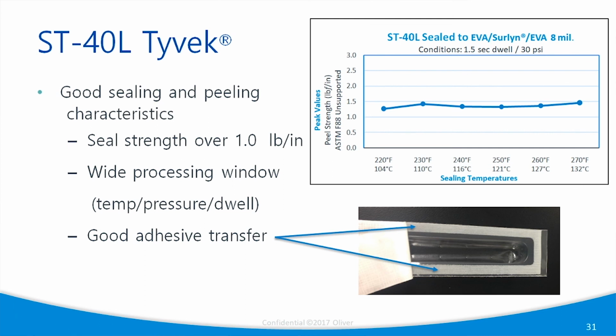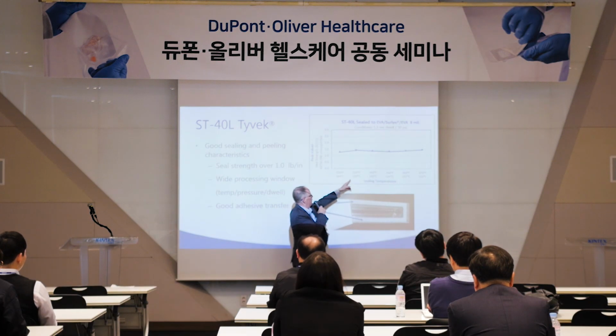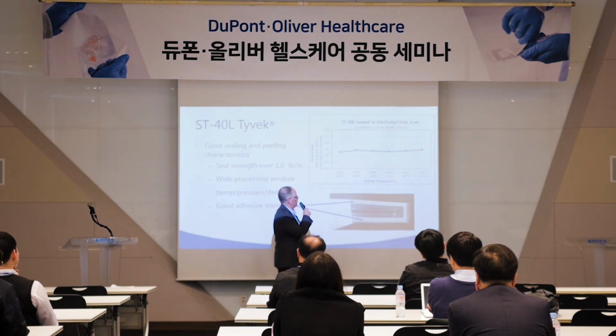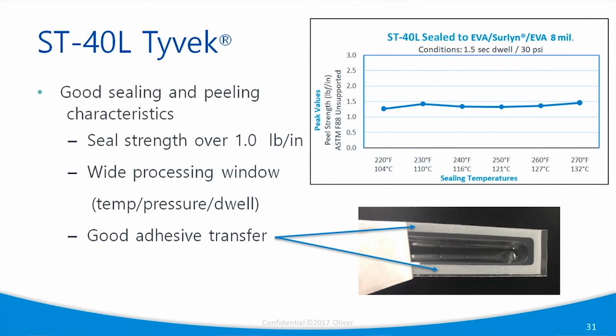That's a nice seal curve we've generated with a flexible forming web, but we're getting values between 110C all the way up to 127, 132C, and peel strength output well over a pound, so that's impressive to us. And then the adhesive transfer properties combined with our coating also look very good. That's a picture of a peeled open form-fill seal package.